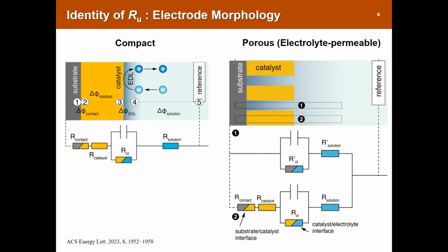If not, you will get the wrong resistance value. Yes, if your substrate is conductive, let's say nickel foil, with the oxide catalyst layer on the front side and metallic nickel on the back side, you are mainly getting the RU through the solution resistance to the metallic part.